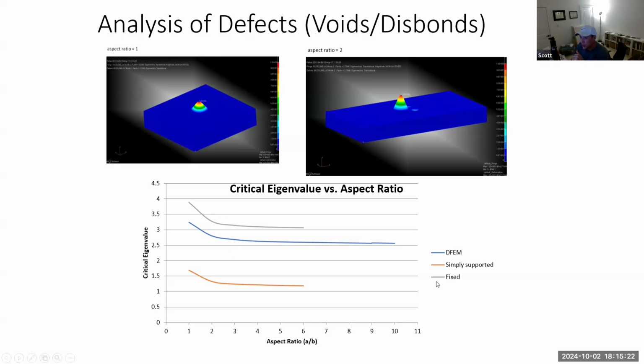What this slide is supposed to represent is that we use a FEM because the previous example, this paper, is a closed form solution, so you can only idealize the boundary conditions as either 100% simply supported or 100% fixed. Those are idealized boundary conditions, but in reality, when you look at the part itself, the boundary condition is neither of those. It's somewhere in between. And our FEM shows, relative to the analysis results from the paper, that indeed the FEM is in between the fixed and the simply supported, closer to the fixed actually. But that's what we want to see. If it was above or below, then we would know that our FEM has some kind of issues. But yeah, it's in between, which is good.